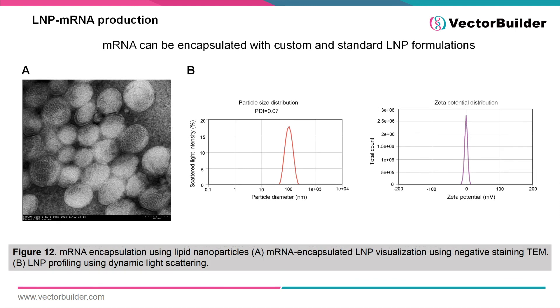Following purification, VectorBuilder offers lipid nanoparticle encapsulation with standardized and custom LNP formulations. Lipid nanoparticles are essential for delivery of mRNA into the cytoplasm of cells, and their formulation and production drastically influences their ability to deliver mRNA. Figure 12 shows LNPs produced at VectorBuilder profiled by dynamic light scattering. As seen here, the LNPs produced have high homogeneity, around 100 nanometers in diameter, which is essential for proper delivery of mRNA.